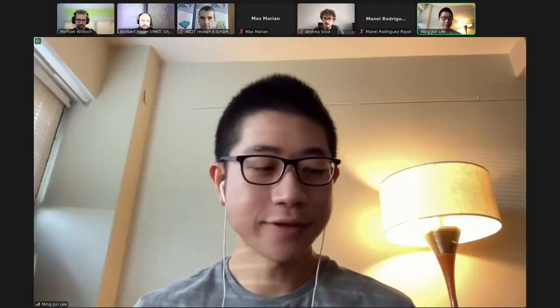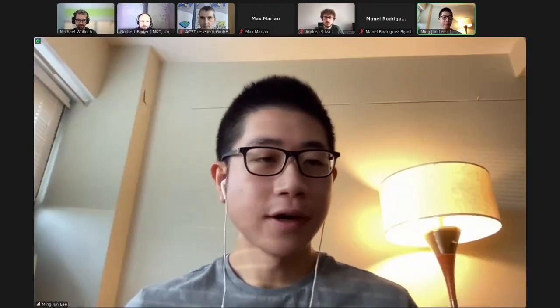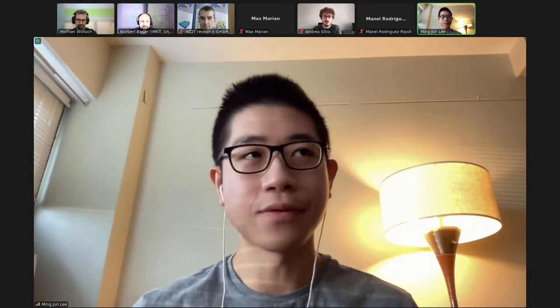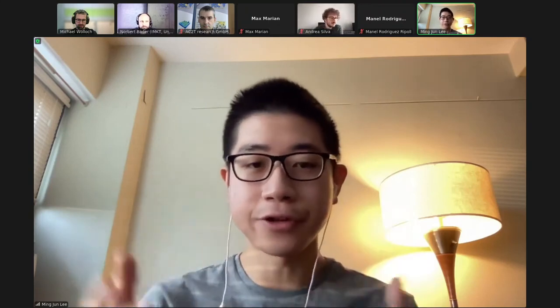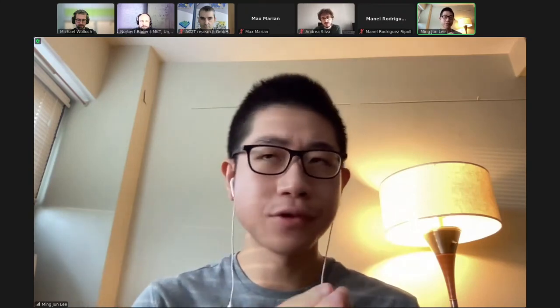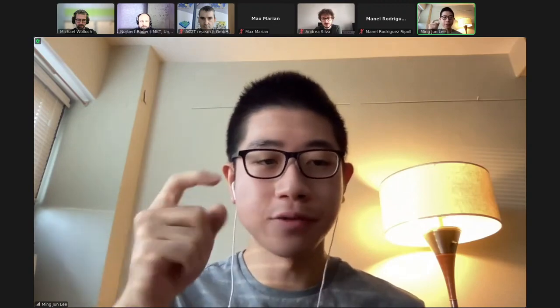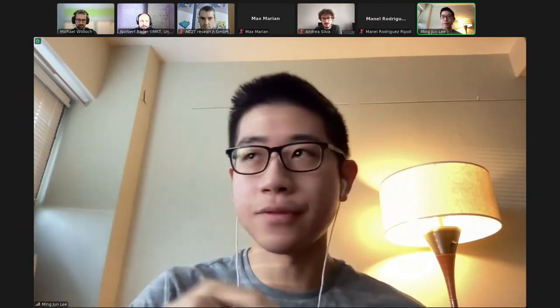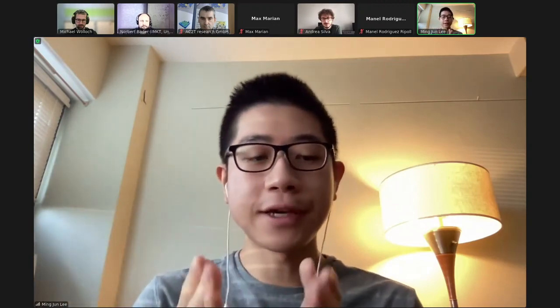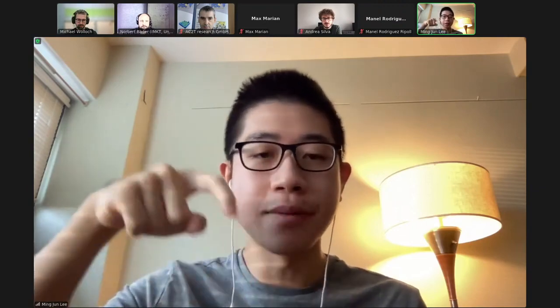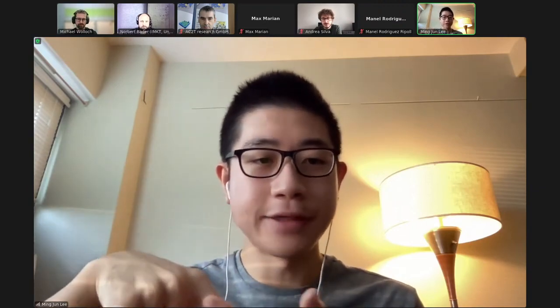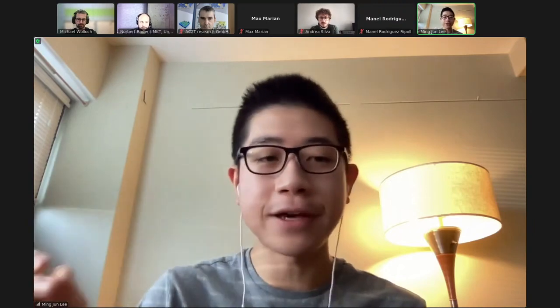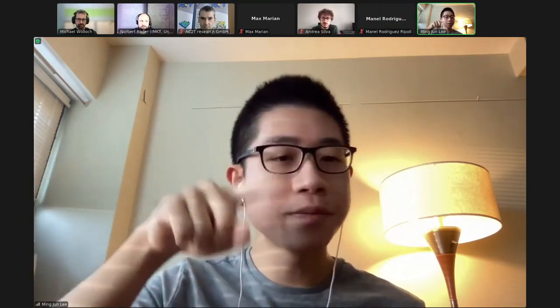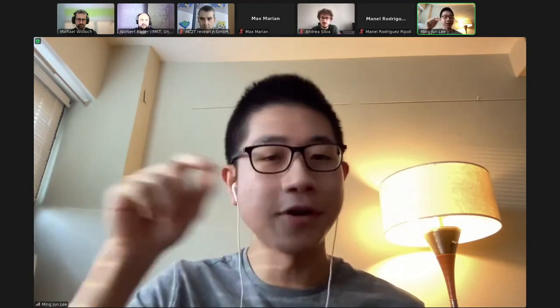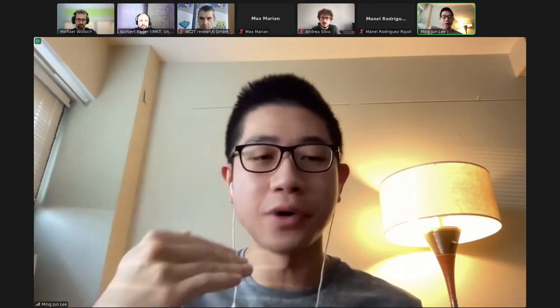Okay, so to answer the first question regarding scale effects, one particular problem that we have when we try to measure hydrogel friction with a tip is that if you use too small a scale, so maybe a very, very sharp tip that we can purchase, you will actually puncture into the mesh of the polymer network. And then you get a lot of stick-slip effects, and the friction maps turn out to have a lot of overblown pixel values. You just see white spots everywhere. So that's the small extreme.